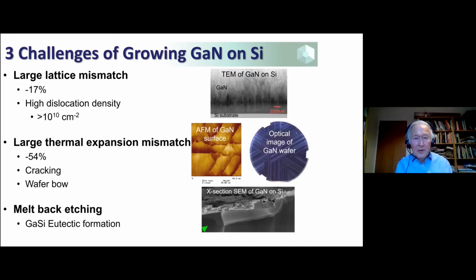And when you cool down, this thermal expansion mismatch is really important. And the gallium nitride is in tension, and so it cracks when you cool down. And the wafer also bows. And the third problem is you can't, in fact, grow gallium nitride directly on silicon because a gallium silicon eutectic forms, and that also etches away at the silicon wafer. So those are the 3 basic science challenges we had to solve to grow gallium nitride on 6-inch silicon wafers.